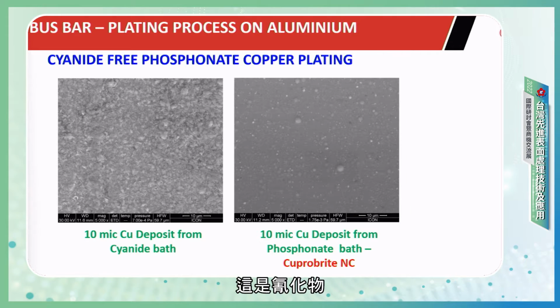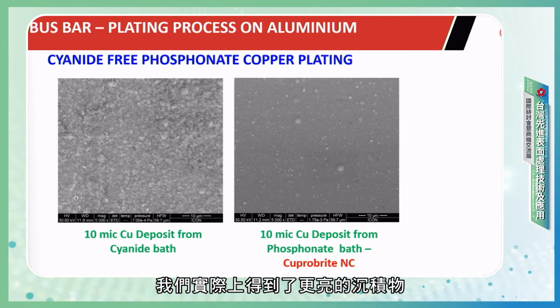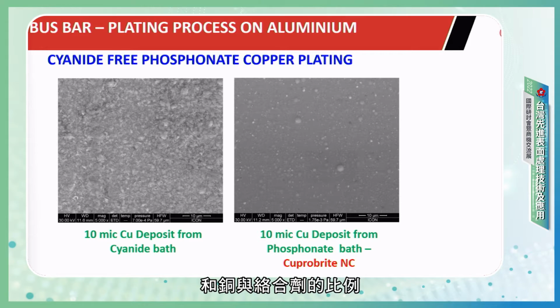This is the surface topography of cyanide versus non-cyanide. Non-cyanide deposits have fine grain with globular, occasionally globular structure, and therefore we get a little bit brighter deposit compared to cyanide copper, but the deposits are very, very compact.